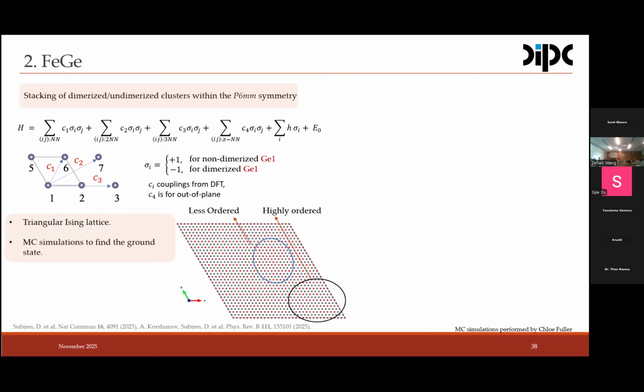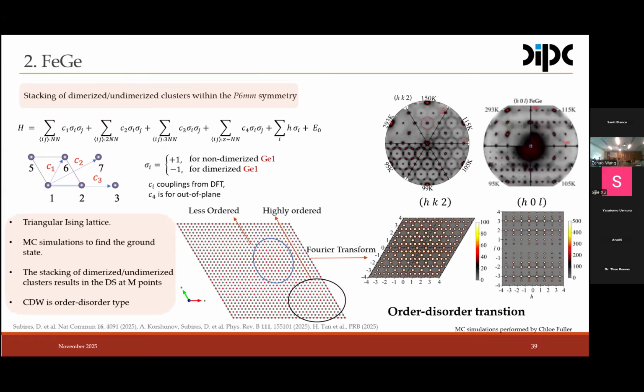So if we do this and minimize the Hamiltonian, we end up with a configuration which looks something like this, right? But there are regions of the space where they are highly ordered and regions where they are less ordered. But then if we do the Fourier transform of this configuration, we can actually come out with the same diffuse pattern, the same diffraction pattern, as we have experimentally observed.